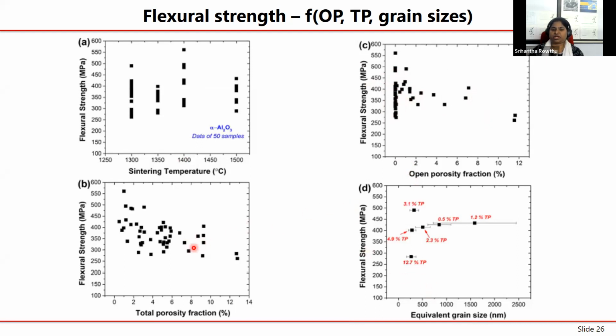But do remember, guys, in your samples, it is not only the porosity that is changing, but the grain sizes are also changing, and they are not changing in a particular trend. So it is important to deconvolute this effect of porosity and the grain sizes. So for example, look at this particular diagram. If I try to see what is the grain size of this one, then this is actually this point here. And if I say what is the grain size of this one, so this is this point here. So you can take selected points in this particular diagram and try to plot, trying to understand if at all maybe there is a special trend where the flexure strength is depending on the grain size. It seems to have some sort of a trend like this, but again, this is an outlier. So it is very difficult to interpret in that way. As long as only one parameter doesn't change, it's a little bit difficult.